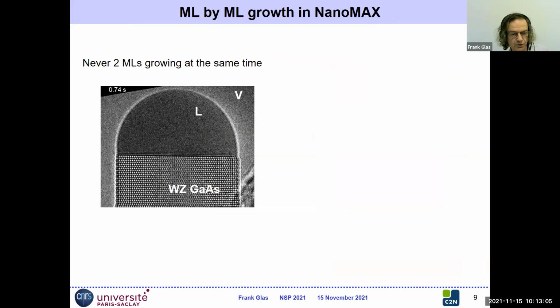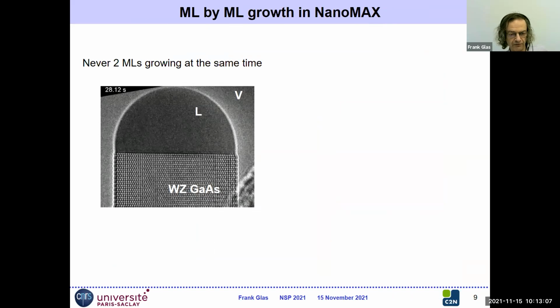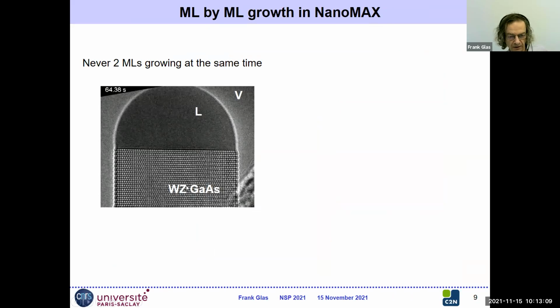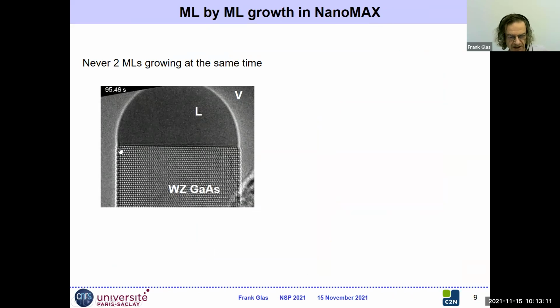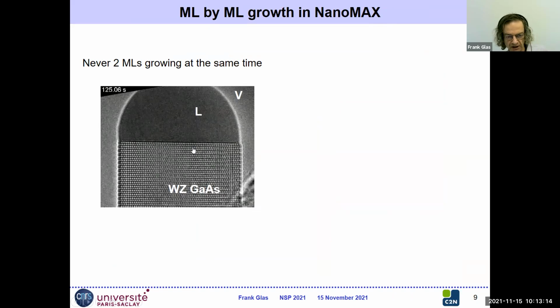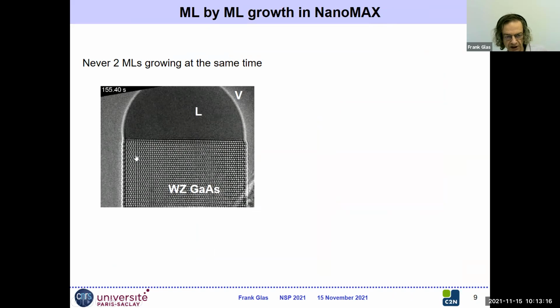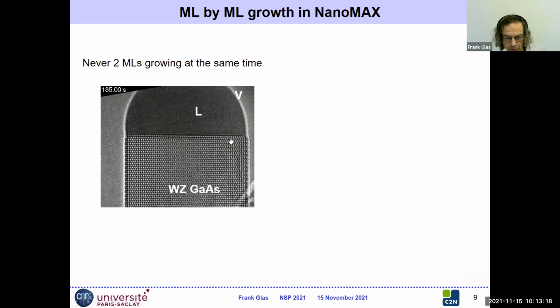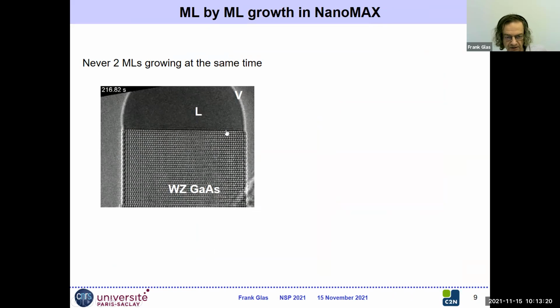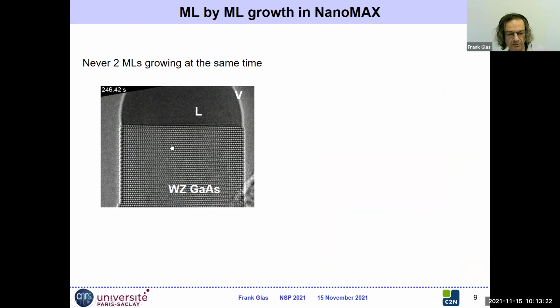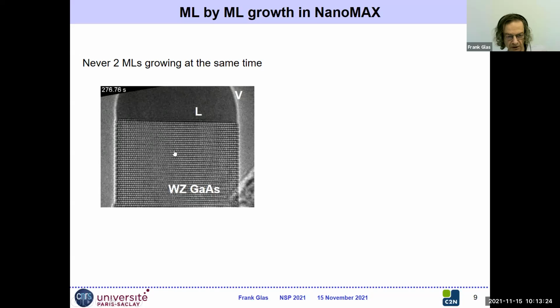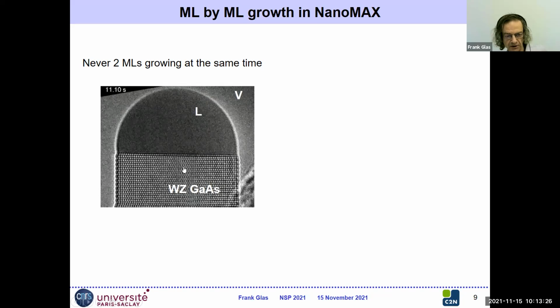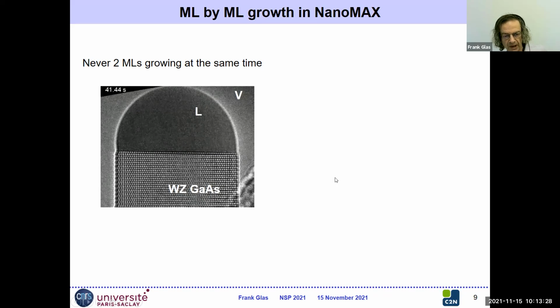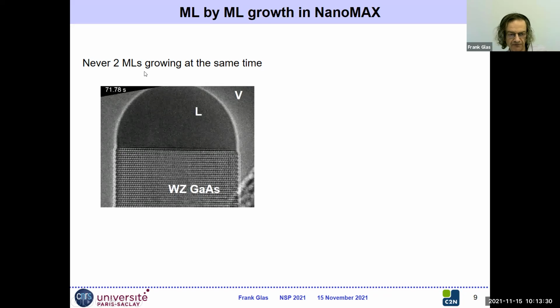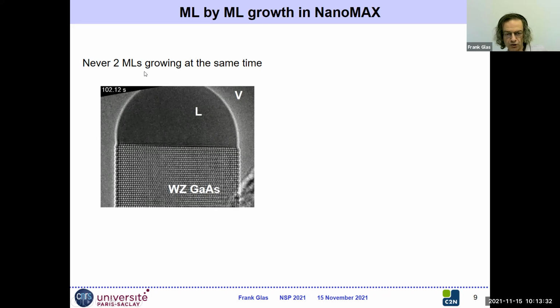Now, what do we see in NanoMax? So this is a view of a gallium arsenide wurtzite nanowire. In the case of wurtzite, I'm not going to speak about this today, but the interface between the solid and the liquid is flat. And you see monolayers which are added at the interface between the nanowire, which is already formed, and the liquid. So here you see them. What is clear from this is that never two monolayers grow at the same time.